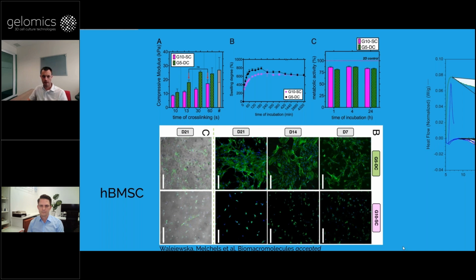So I think viscoelasticity is kind of a phenomenal measurement. You measure the mechanical properties, which are a result of the microstructure, and the cell behavior is also a result of the microstructure. So they're both a result of the microstructure. So I don't think you can say this viscoelastic property or behavior will lead to this kind of cell behavior. But it's definitely an important measurement to do.